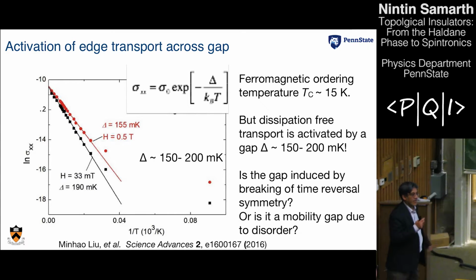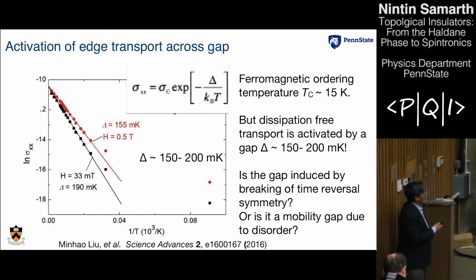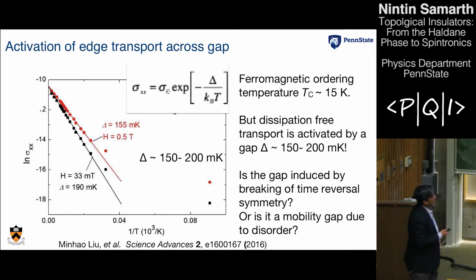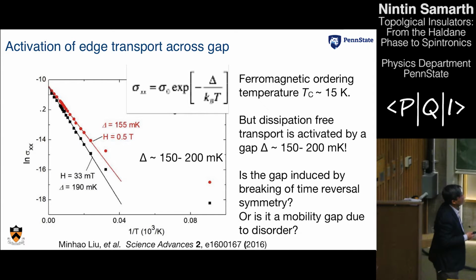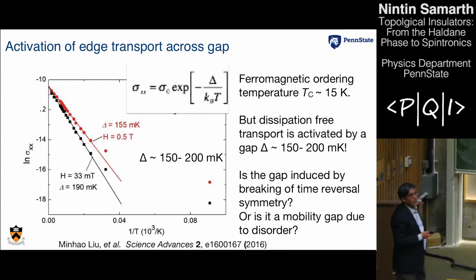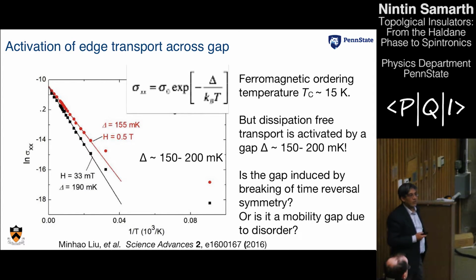And what happens then is that from this dissipationless state, you're getting thermally activated transport that is dissipative. And so if you plot the natural log of the longitudinal conductivity as a function of 1 over temperature, you get activated behavior over some range of temperatures. And from this activated behavior, you can pull out a gap. So despite the fact that the ferromagnetic ordering temperature is of the order of 15 Kelvin, the gap is very, very small. It's only of the order of 150 to 200 millikelvin. So this is quite surprising.